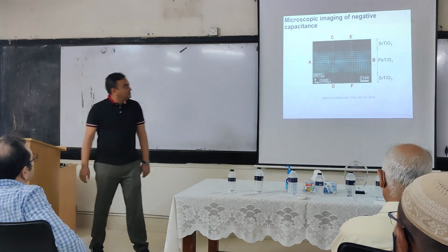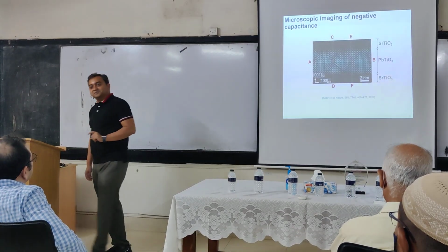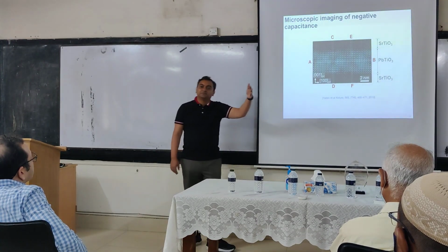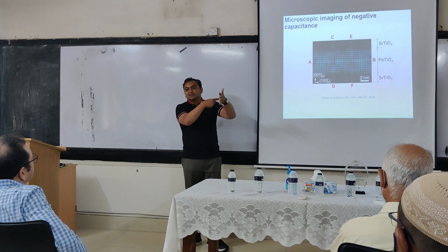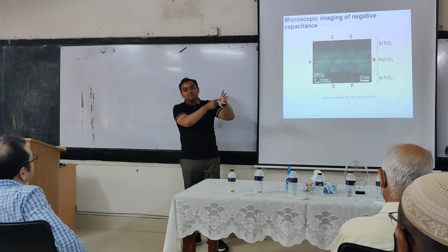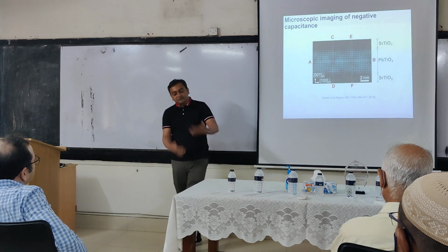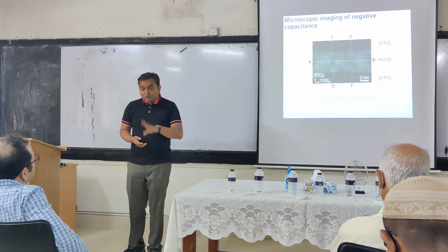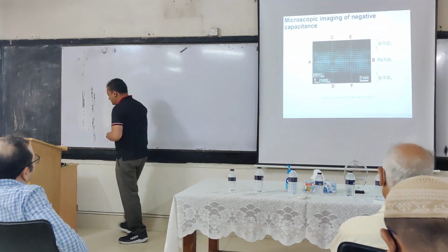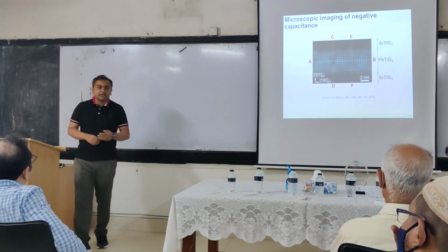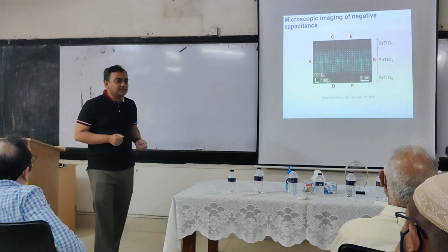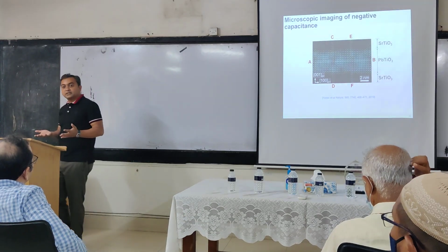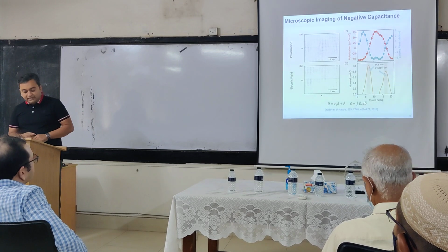Okay. So there is a way to measure the electric field. How? Let's say I have an electric field inside my material. Let's say I put an electron beam on it. What will happen? The beam will deflect. So if you have a very good detector on the other side, by looking at the beam deflection, you can figure it out. So exactly, most textbooks were written 30 years ago. We did not do that at that time, so they will say we cannot measure the internal electric field. Actually, we can do everything by using these electron beams. Okay, not by using a voltmeter, but using the electron beam. So we do that, and we can figure it out.